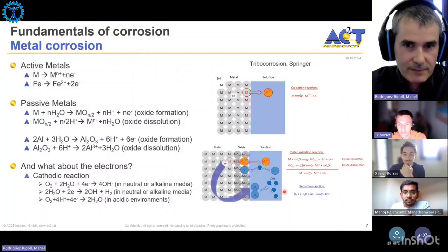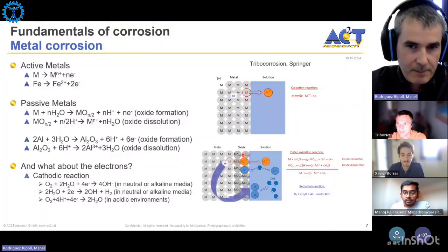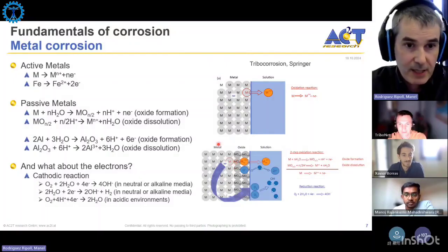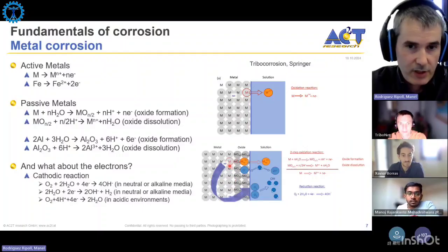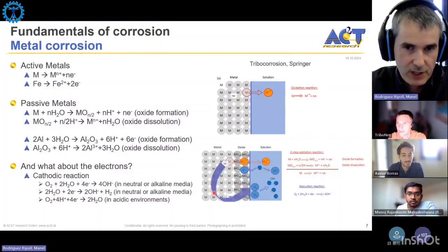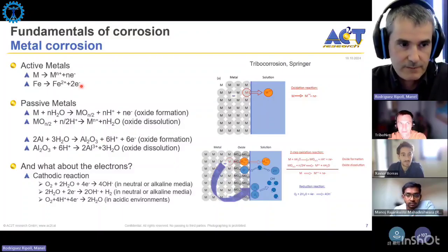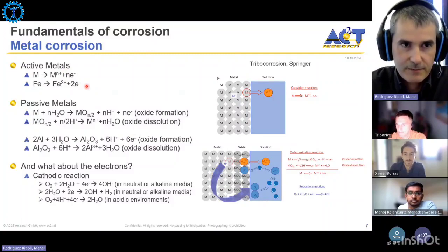That layer, is it weaker? This layer in passive metals typically is a few nanometers thick, maybe 2 to 5 nanometers, and it depends on the conditions, how this passive layer is formed, and the electrolyte where the material is immersed. But typically it's a ceramic. For example, in aluminum it is aluminum oxide, in titanium it is titanium oxide, but it can break during rubbing, and it does break. When you break this passive layer, you expose the naked metal to the electrolyte, and then the corrosion rate will not be this one, but will be something closer to this. So that's the point here.